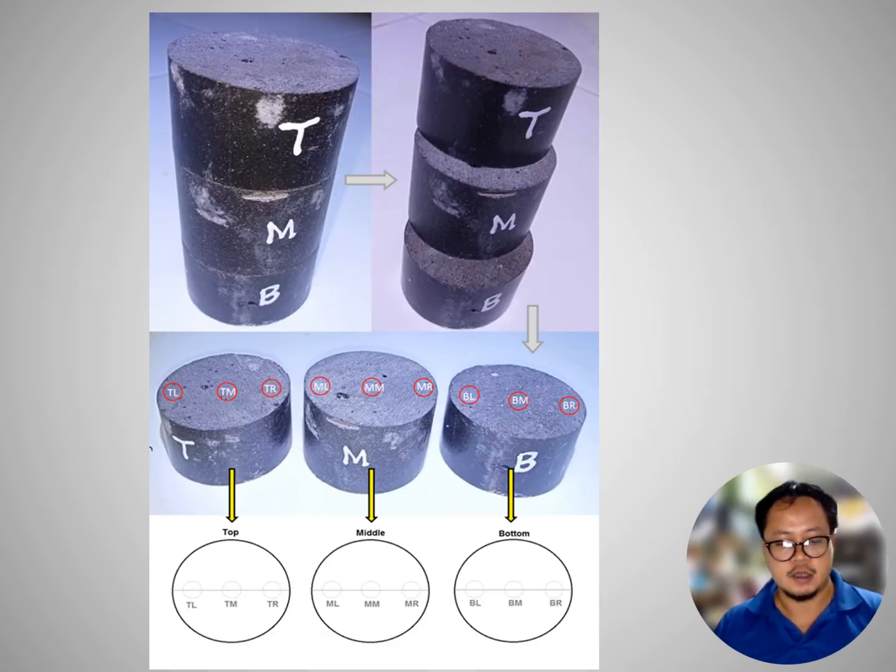And this is another variation of test sample which involves a saw cut. For saw cut, the test sample was cut at 2 points to produce top, middle, and bottom sections in the transverse direction. Each of the sections was further divided into left, middle, and right areas. So each section will have 3 locations, which in total is 9 locations involved in the magnification of the image.